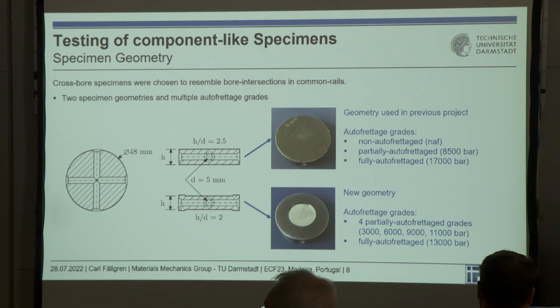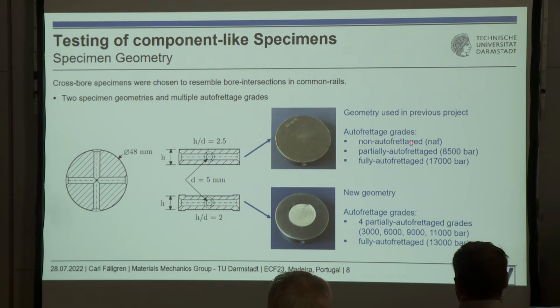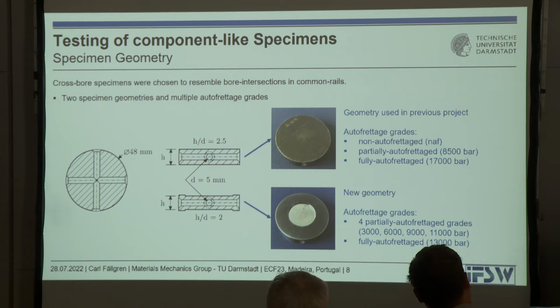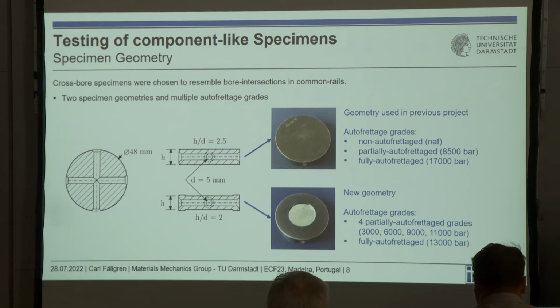We have this geometry, which is the original geometry, I would call it. It was used in a previous project where it was tested with 42CrMo4. We had three different autofrettage grades: non-autofrettaged, partially autofrettaged at 8,500 bars, and fully autofrettaged at 17,000 bars, and this is approximately 92% of the bursting pressure of this component, which also was tested experimentally and calculated numerically.